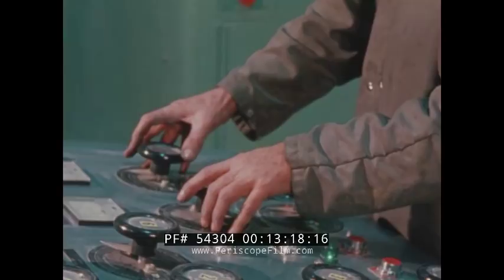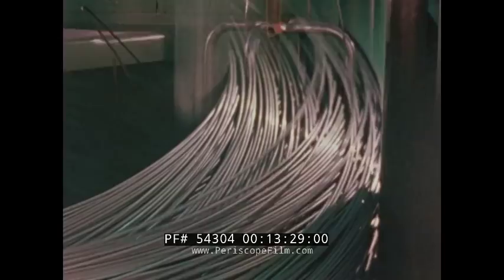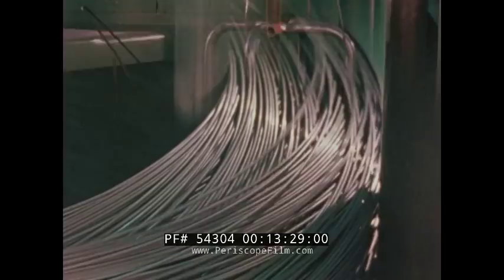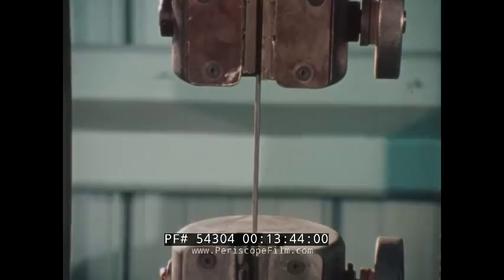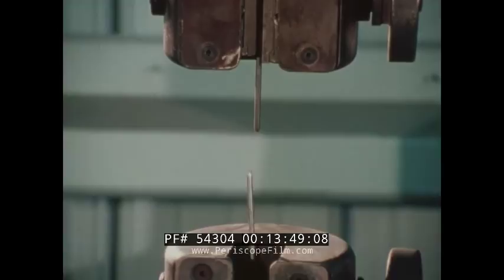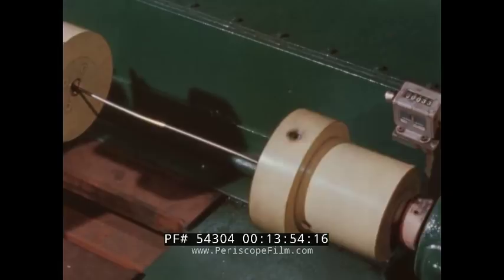Following the last draft, wire is fed through a dead block and dropped in dead cast rings onto the carrier. All quality control checks take place before packaging and shipping, including tests for mechanical properties such as tensile strength and elongation. Strand cast steel has resulted in a record low of rejections. Other tests might include checking torsion requirements, or inspections for hardness, size, and finish — all aimed at careful determination of the wire's fitness for the service required of it.